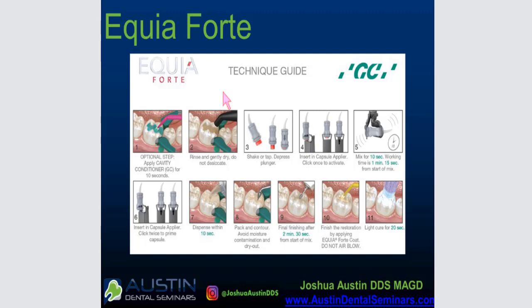You're going to gently dry it. You don't want to over dry this. It's a lot like composite. Over drying is bad. Tap the little button in, depress the plunger, throw it in a triturator or an amalgamator, and that seems to be the problem with this material, is that many people do not have amalgamators anymore or mixers, and I totally get it.